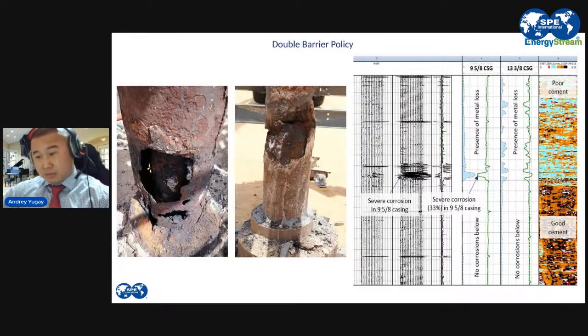It can corrode in between two casings. That's what you can see on the right side on the log. What we can see here is an MBRT log of Baker Hughes. The leftmost log is our discriminator, where we can see there is a hole, and then the flux, the main sensor, shows that there is a massive external corrosion. If we try to understand why exactly it happens at this depth, on the right side you can see the cement bond log, and what we can see is the interface between good and bad cement.